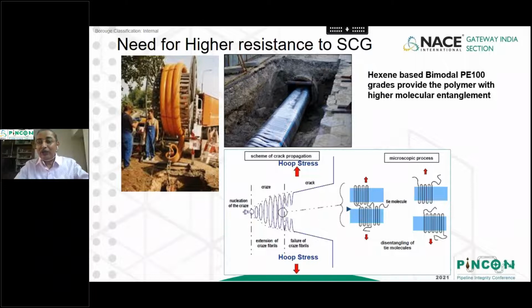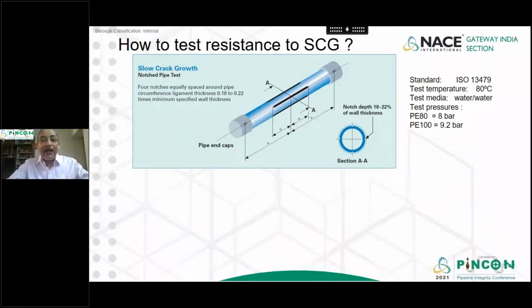Therefore, hexene-based bimodal PE100 grades provide the polymer with higher molecular entanglement and give 50 to 100 years service life despite notches and scratches and surface damages. How is SCG resistance measured?